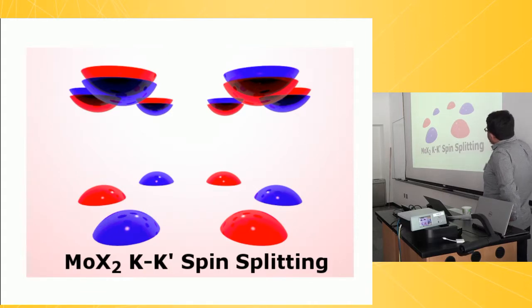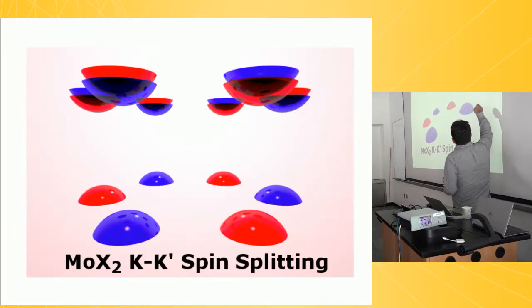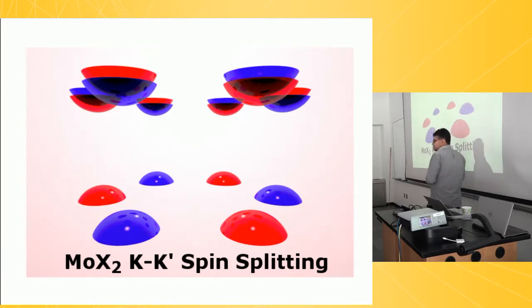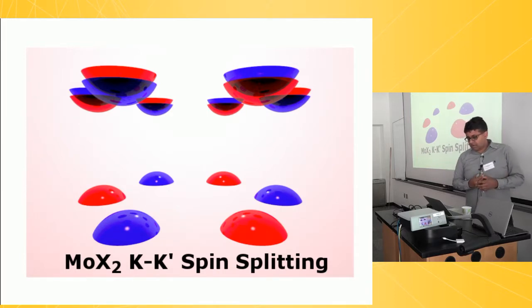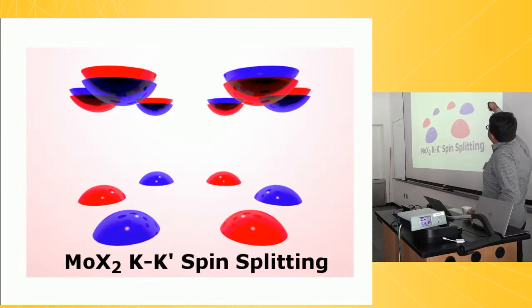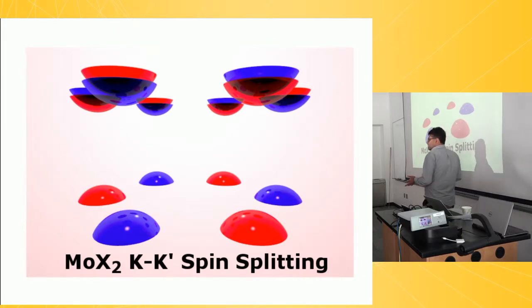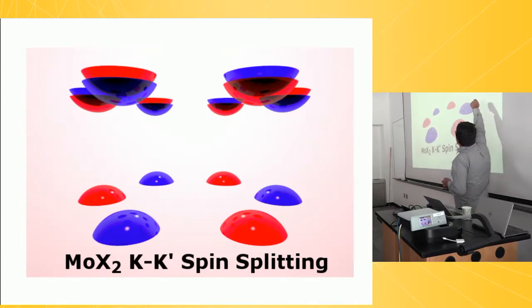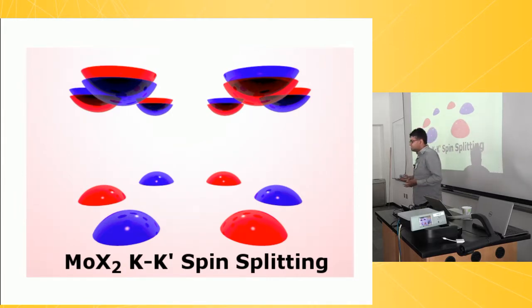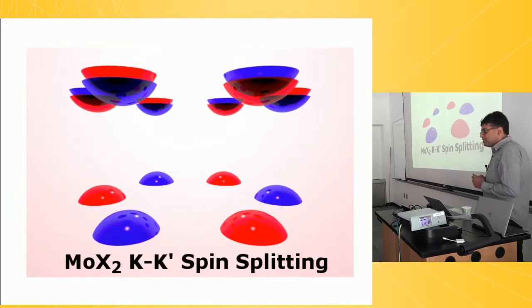For example, if I take this material, which is the molybdenum-based TMD, then the spin structure at any of these values is the same for the top of the valence band and the bottom of the conduction band. And what this means is that this transition from this lowermost state from here to here is optically bright. So you have light emission. Now imagine I start with t equals infinity. At t equals infinity, I'm going to populate both the blue guy and the red guy equally. And half of these are bright, half of these are dark. As I start cooling it down, all of my electrons are going to be sitting here. And so I get more and more emission because the population of the bright guys is increasing, until eventually at low enough temperature, everything is bright.